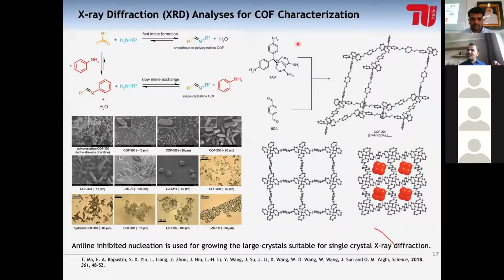And now this is a common Schiff-base reaction which we do in the lab every day. And in this case, we know exactly where the nitrogen should be sitting. Exactly over here, there is a nitrogen. There is another linker which is coming from here. So this is the advantage of crystalline material. These are really smart materials because you can predict the properties of the material by using different organic molecules. We can induce something inside. For example, I can put any fluorine molecule, any molecule here, and I know where exactly this molecule would be